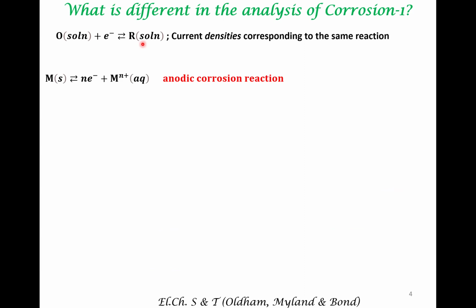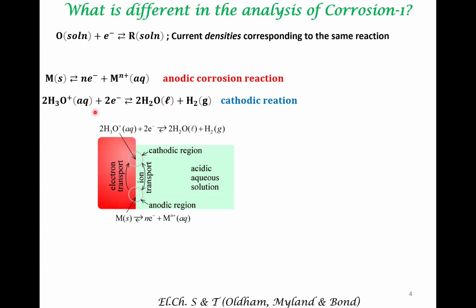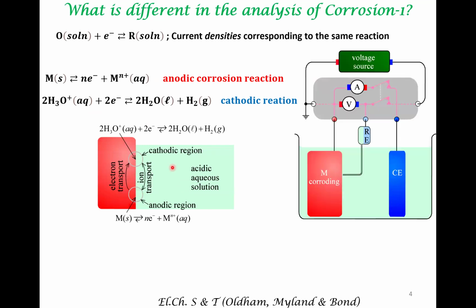In contrast to this, corrosion involves two different reactions. There is an oxidation, metal gets oxidized. This contributes to the anodic corrosion reaction. And there is a distinct reaction which is contributing to the cathodic part of the corrosion reaction. Okay, so this is one reaction. Here in corrosion we have pairs of reactions. This is the central difference, and this has implications in the way we think about currents in a corrosion cell. Note the corrosion cell. In a corrosion cell, the anodic region is not separated from the cathodic region. So despite this issue, the electrochemistry can be well studied via this setup.